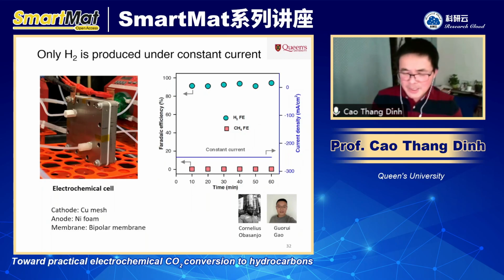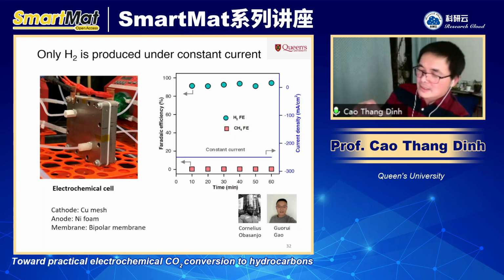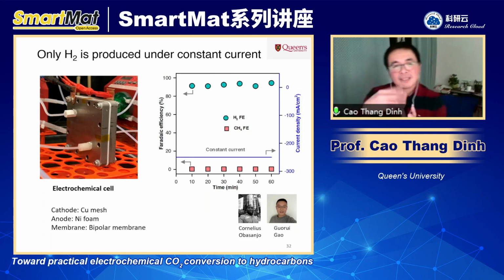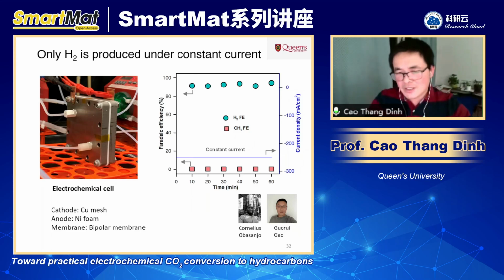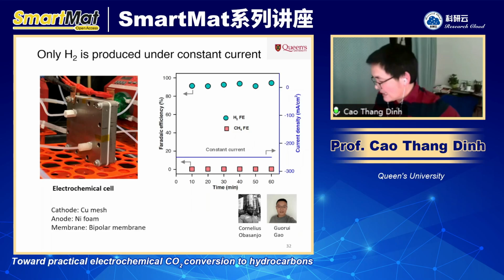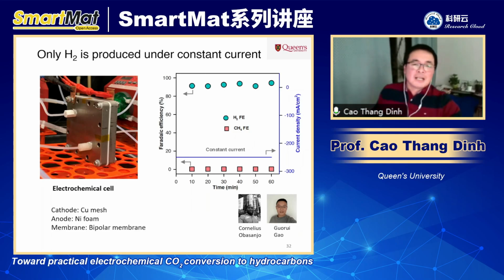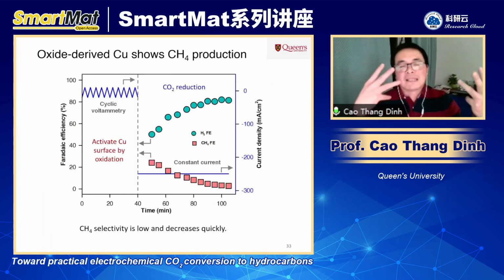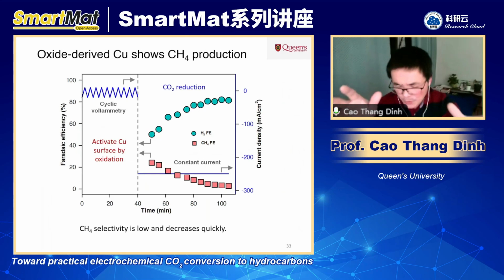Professor Matt Kanan at Stanford, like 10 years ago, already discovered that with a copper surface, if you oxidize it a little bit, you can improve the selectivity of CO2 conversion, right? So we did exactly a similar thing. We tried to oxidize the surface. Let me explain this graph and how we did it.